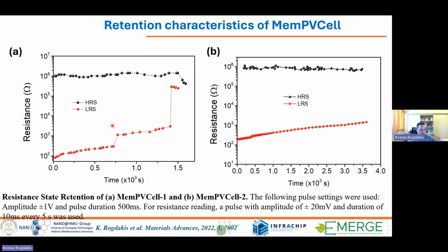Another typical measurement is the retention characteristics. So here you set the device to the high resistance state, for example, and you monitor the resistance state in time until you see some degradation. High resistance state is very stable. The problem comes in the low resistance state, that after a few thousand seconds, the device jumps to high resistance state. So now we have some ways to improve the retention characteristics of the devices, like the plot on the right.